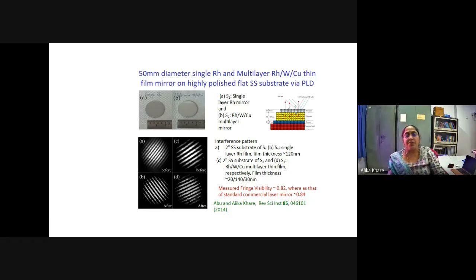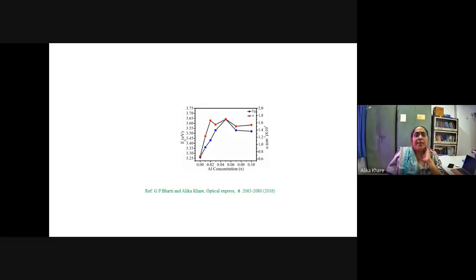So many times people have the perception that with pulse laser deposition, the quality may not have good control. But here we have demonstrated the quality over a 2-inch size, and later I have seen relatively recently that people have deposited films up to 20 centimeter size with very good quality.